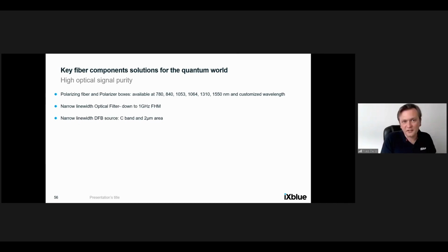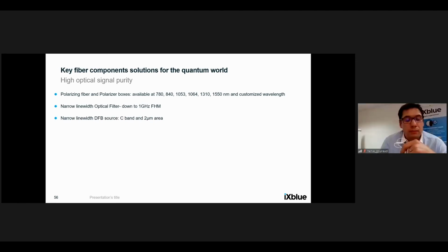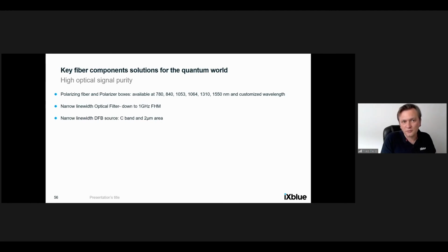And then finally, to get your high optical signal purity, we went over some solutions to increase the polarization of your laser. And there we have solutions available that are standard for 780 nanometers, 840 nanometers, 1053, 1064, 1310, and 1550 nanometers. To customize if there's a need for it. We've shown our capability to provide now optical filters with a bandwidth as low as 1 gigahertz, and the ability also to provide you with the tools to build your own narrow linewidth DFB sources at 2 micron or in the C-band.